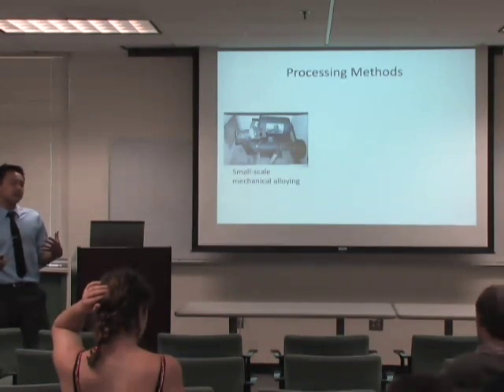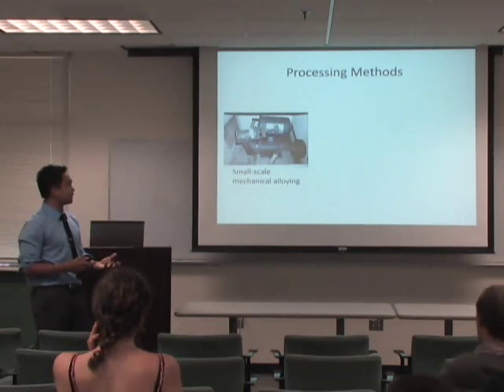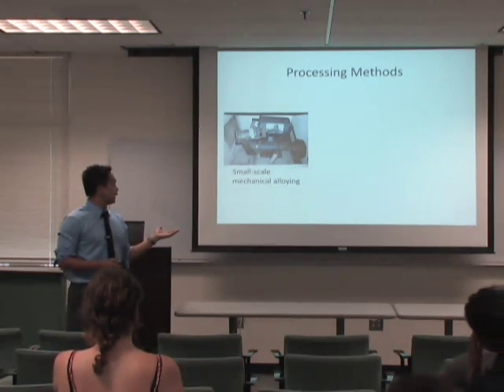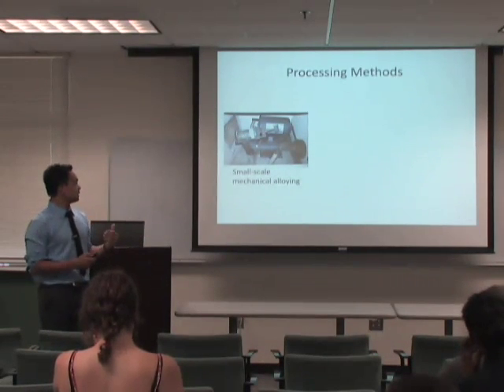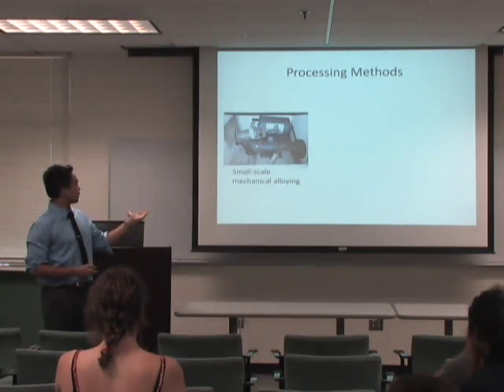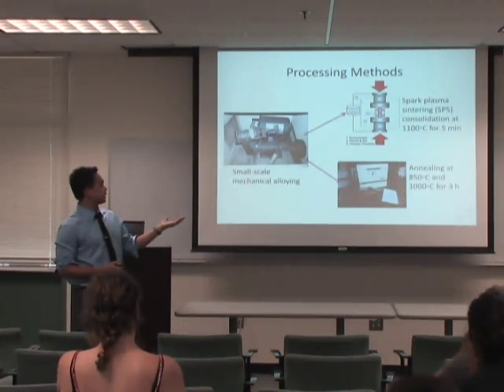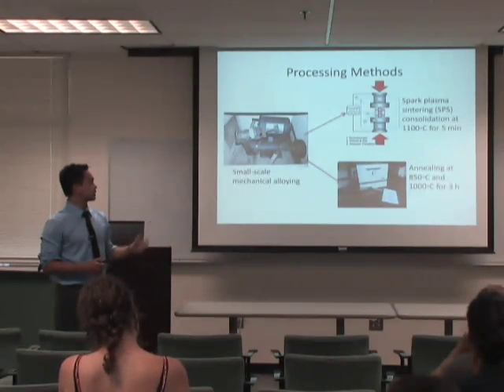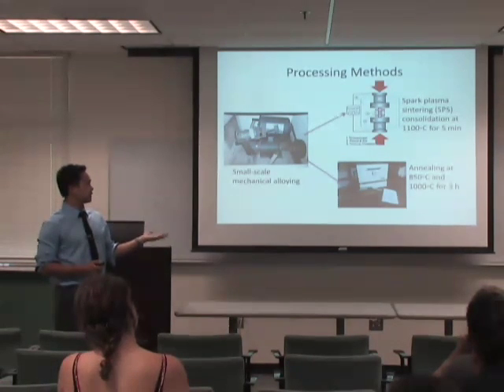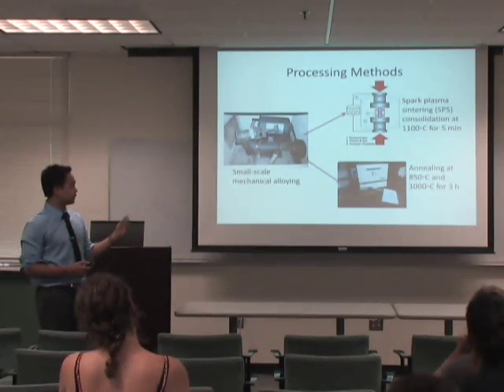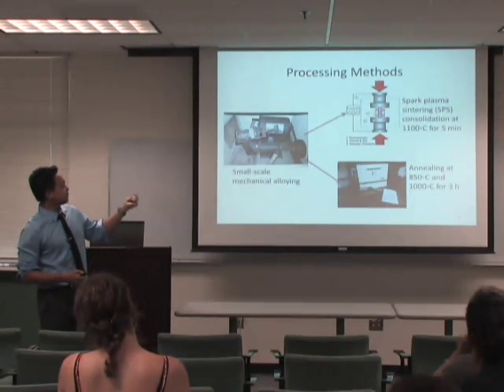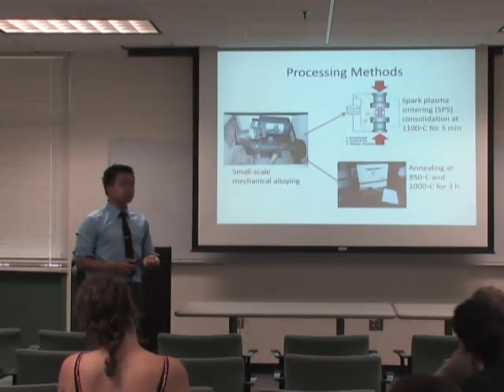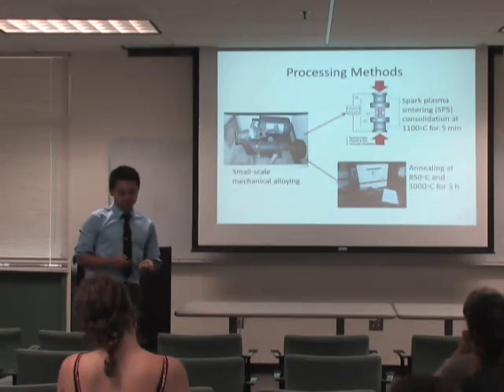And to mimic the processing technique of these yttrium NFAs, I've also mechanically alloyed my scandium NFAs, or scandium powder with the iron powder. Then I've heat treated using 2 different techniques: 850 degrees Celsius and 1,000 degrees Celsius for 3 hours in a furnace. And I've taken some of the powder and actually consolidated it at 1,100 degrees Celsius for 5 minutes.